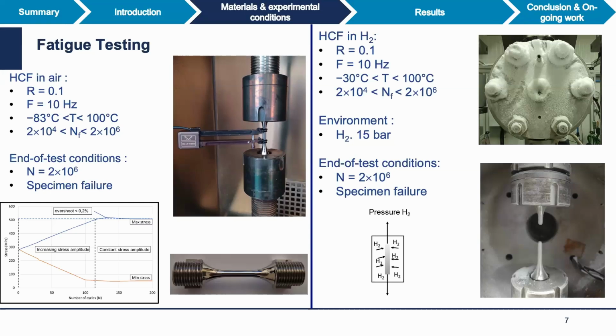And typically the fatigue life that we target lies between 2×10⁴ and 2×10⁶. And the tests are rated as stopped in any case for this value of the fatigue life. As regards testing in gaseous hydrogen, the loading conditions are the same, load ratio 0.1, frequency of 10 Hertz. So far, we have only data down to a temperature of -30. The pressure of hydrogen is 15 bars.